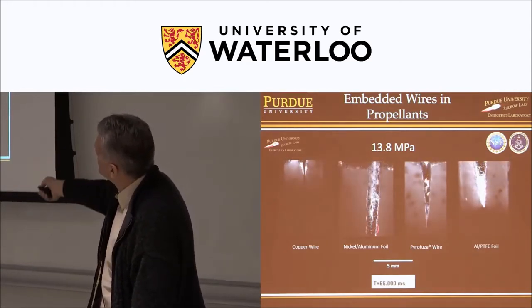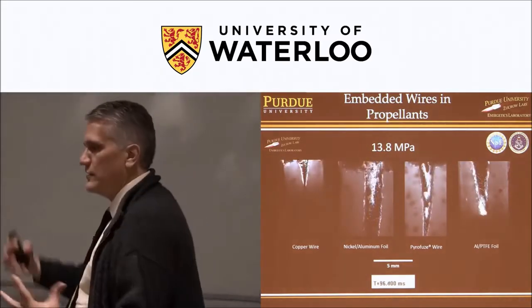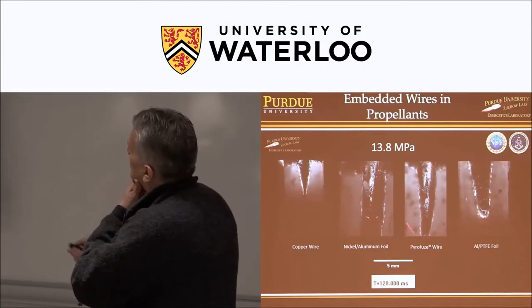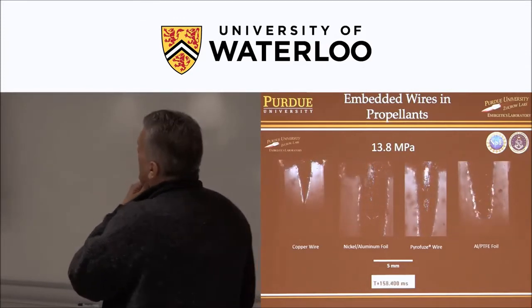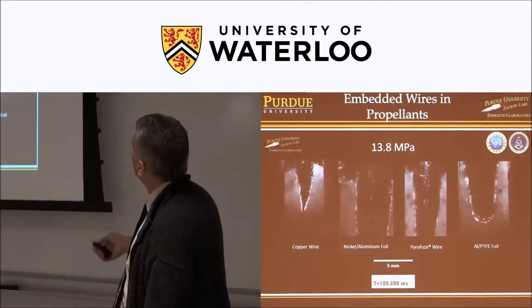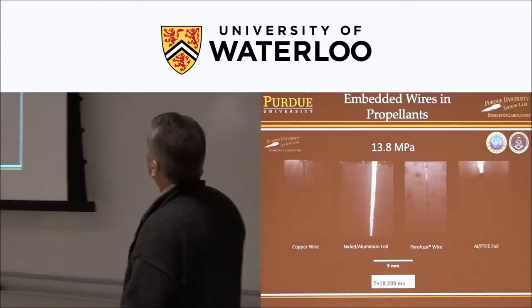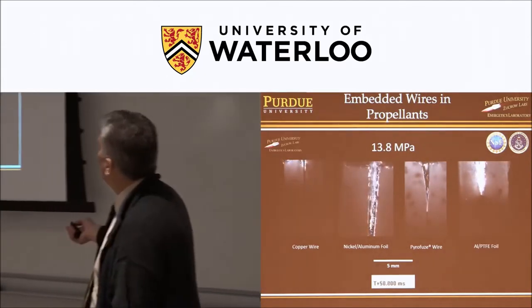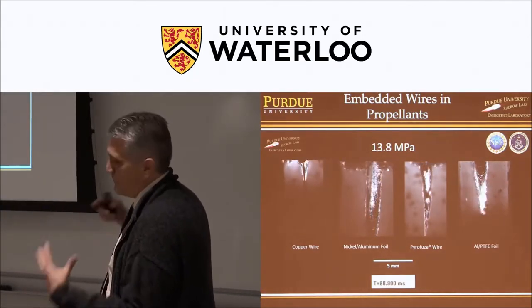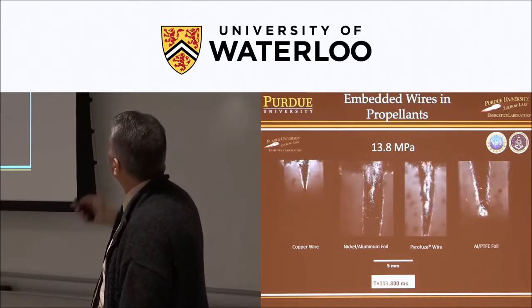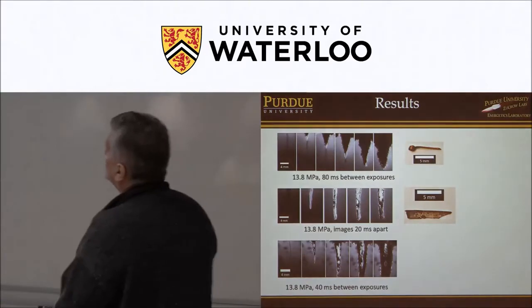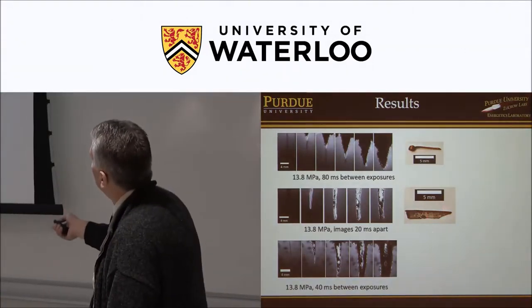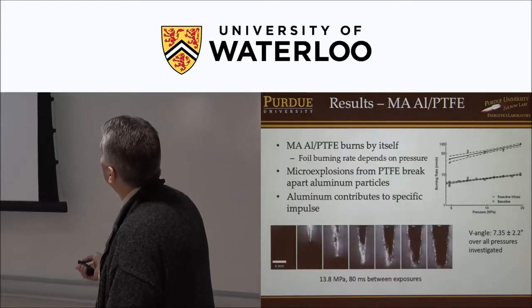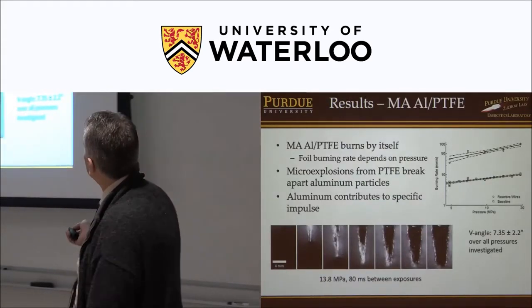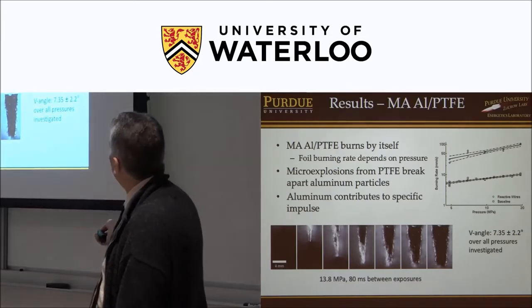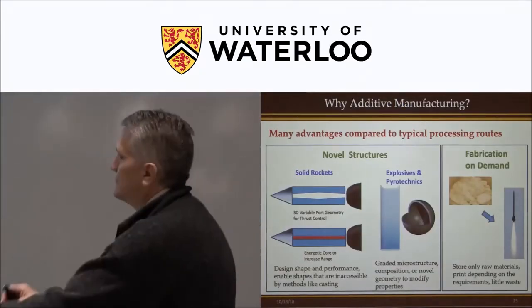The disadvantage of these materials is that in all their cases, they produce products that are basically non-reactive and form big clunky particles that go out through your nozzle. In this case, the particles disperse into aluminum. And as I mentioned before, propellants often use aluminum anyway, so it'll form small droplets and small particles. So this shows you some of the products that come off from these types of experiments. And this is the aluminum Teflon type of material that forms a small dispersive type of thing.